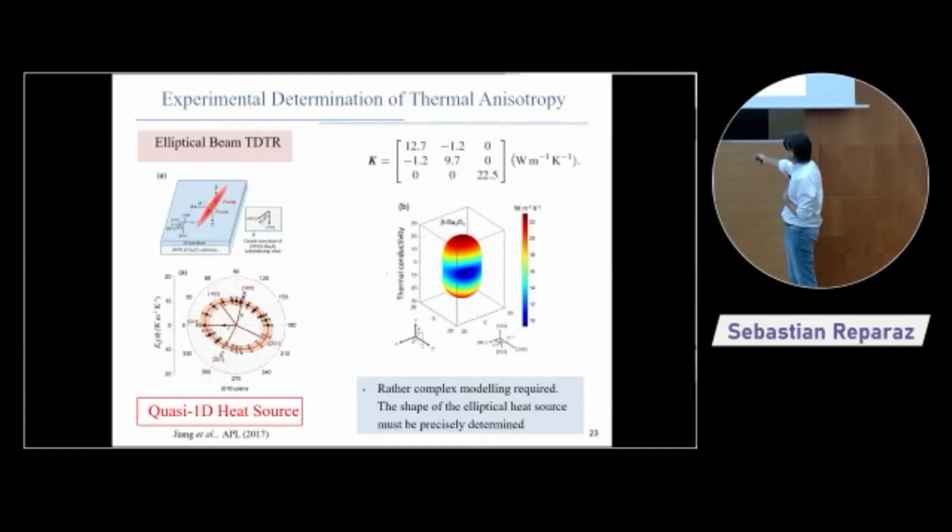And then basically the guys were just turning around the sample or the spot, I don't remember, in order to obtain these maps of thermal conductivity here. The real measurements are only the dark points, and the other ones, the open ones, are just actually reflections. And they have shown that it's possible to reconstruct, and this is actually very beautiful, the full 3D thermal conductivity tensor for the material. There's not a lot of work out there where people can show this kind of thing. This material is complicated.